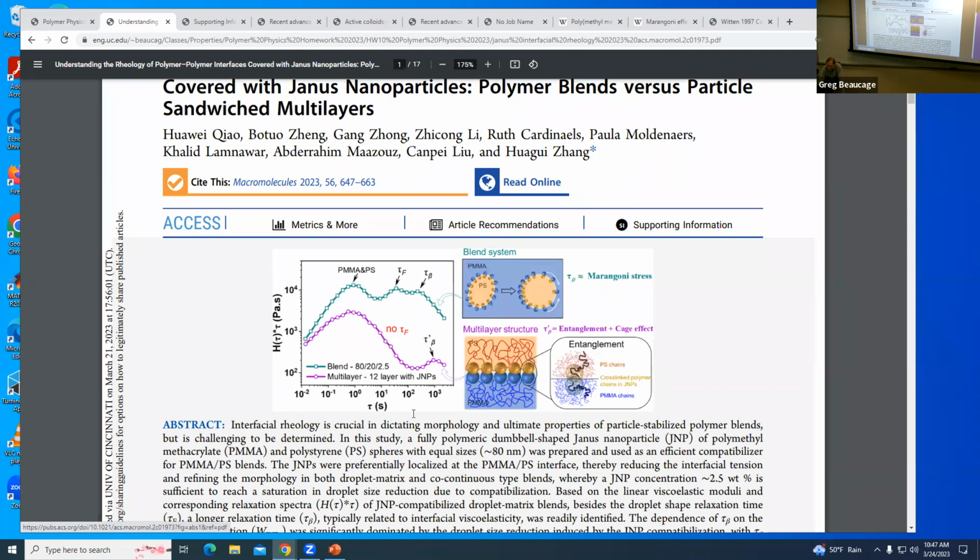using time temperature superposition. Because one thing, time temperature superposition is going to have a problem when you have solid particles in there, because they don't. So say you put 50% carbon black into rubber, right? Well, yeah, there's a time superposition for the rubber. Yes, absolutely. So you can get an AT for the rubber, but the carbon black has none. The carbon black is just a rock, right? So that means half your sample isn't going to time temperature superposition, but you're still shifting it with AT. So something bad is going to happen, right?